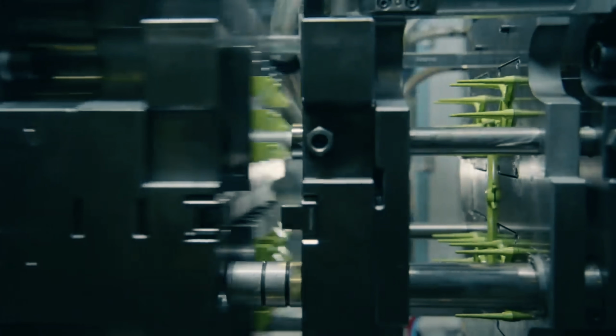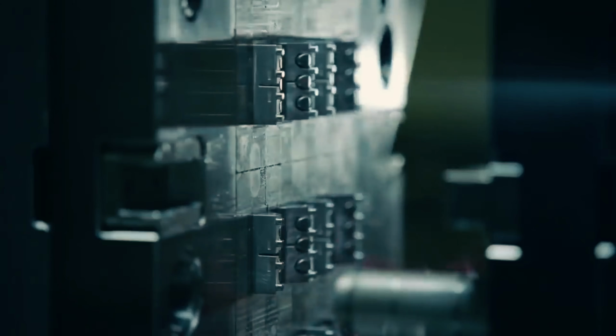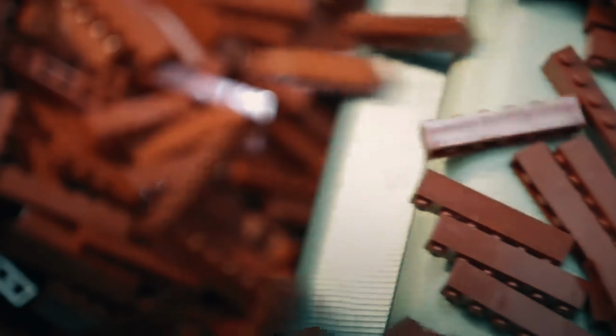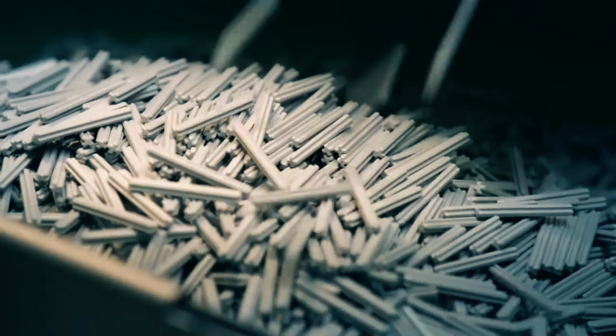The mold snaps shut, plastic floods every cavity in a fraction of a second, and cooling channels built into the steel mold pull heat out almost immediately, hardening the plastic from the outside in. Within 10 to 20 seconds, the mold opens and the finished piece is ejected. Still slightly warm, but already holding its final shape.